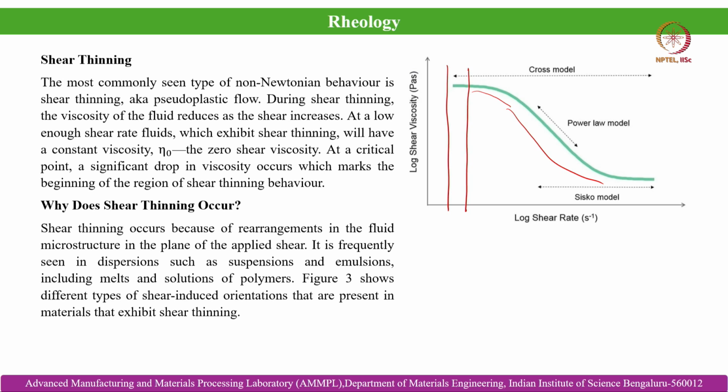So, this is a region where the power law model is applicable, where there is a catastrophic drop in the viscosity of the shear thinning fluid. Okay. But in the whole regime the cross model is applicable.